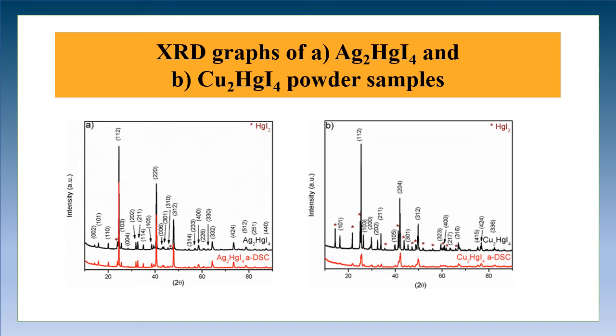After three cycles of heating and cooling in the DSC measurement, the samples were measured by XRD again to study possible degradation. The powder pattern of the silver tetraiodomercurate sample did not show evident change. However, the powder pattern of the copper tetraiodomercurate sample showed much less intense and broad peaks, associated with lower crystallinity in the sample.